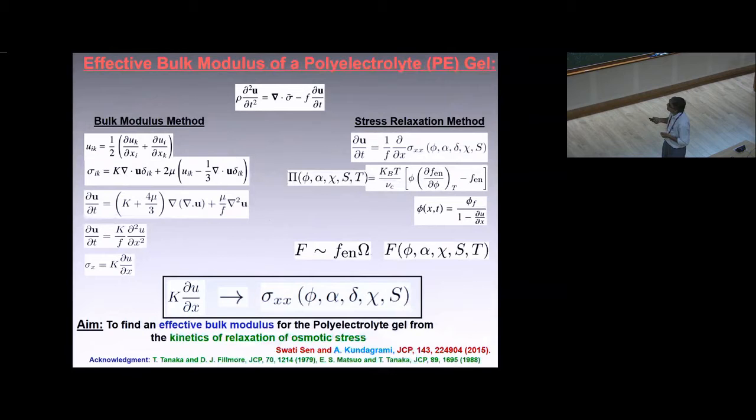There are two methods - one is a diffusion method where you follow basic Lagrangian definitions of elasticity with bulk modulus to the system. In the other method you take a free energy, from that get osmotic pressure, and from these two, comparing profiles, you can find bulk modulus for small deformation. From the osmotic pressure of the gel, which is a function of polymer density, charge density, dielectric constant, chemical mismatch, and crosslink density.